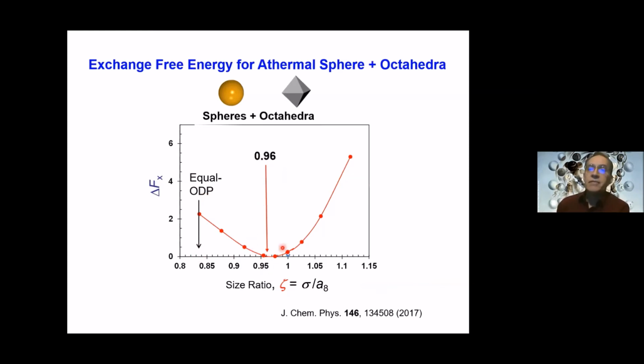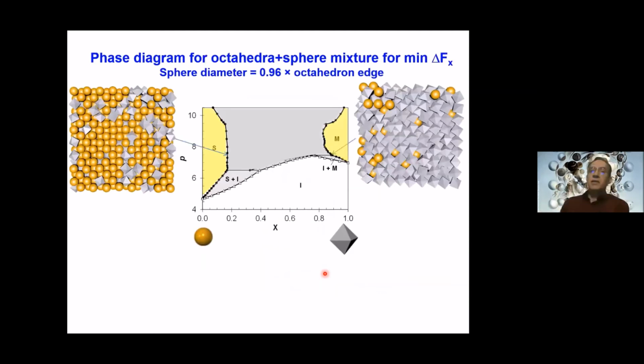So let's see how our phase diagram looks now. So now it looks something like this. So now you can see that, for example, on this side, the Minkowski crystal, the octahedral rich crystal, can dissolve much more of the spheres, almost 20%. But also importantly, on the other side of the diagram, now you can see that the FCC crystal of the spheres can dissolve up to 20% of the octahedra. And that's great. That's really what this rule was designed to optimize.